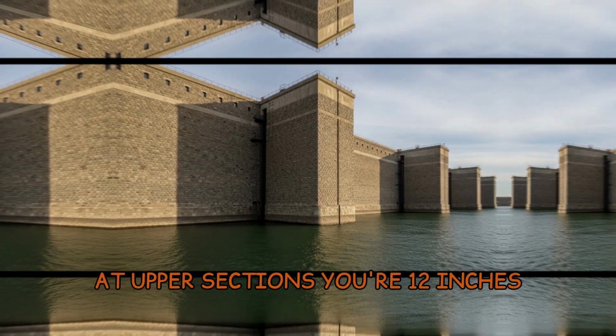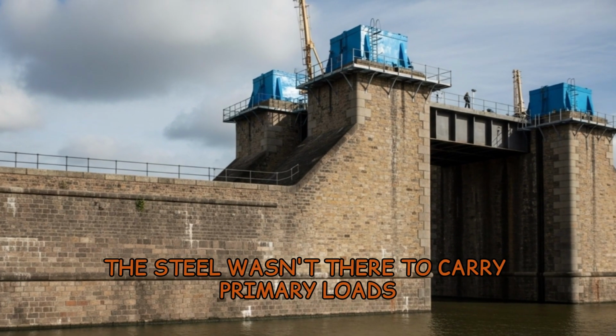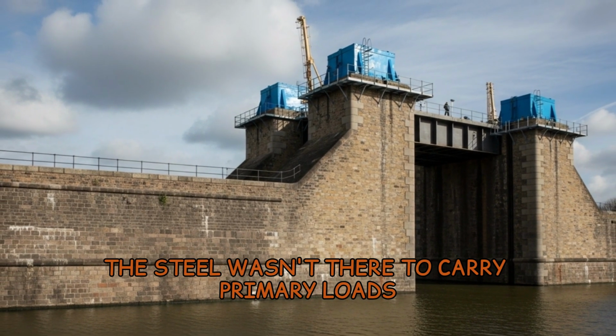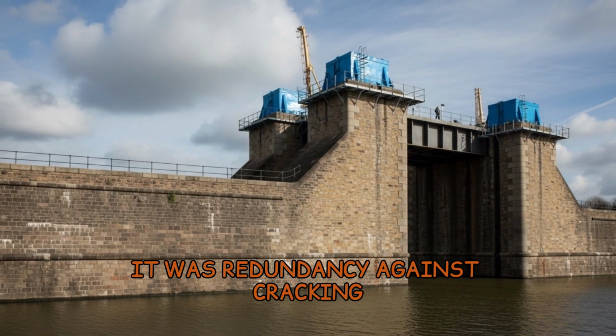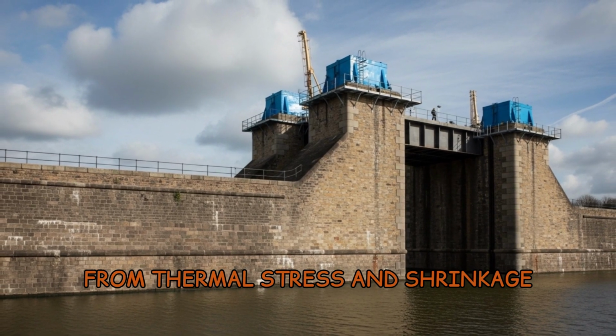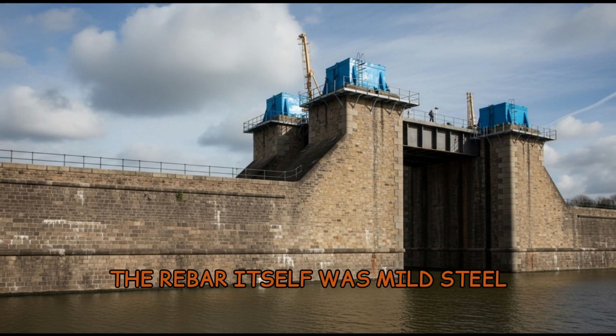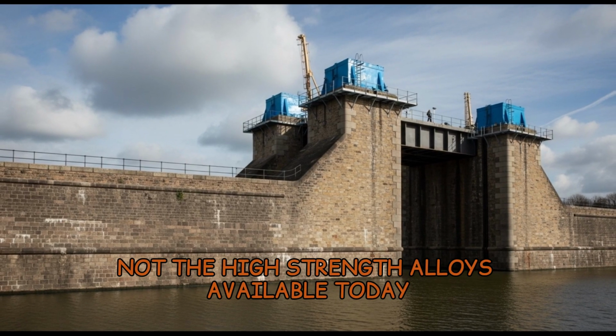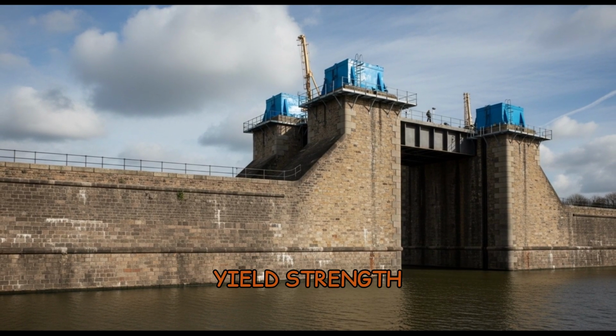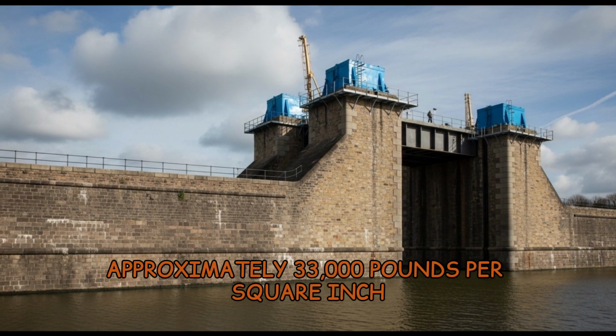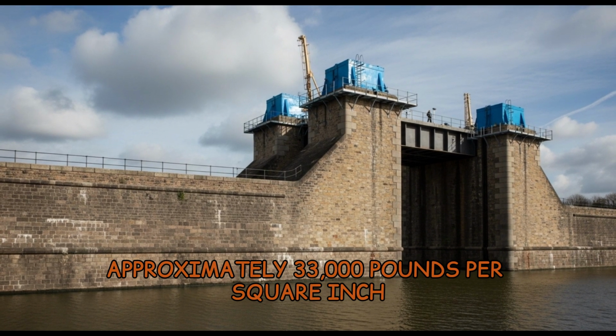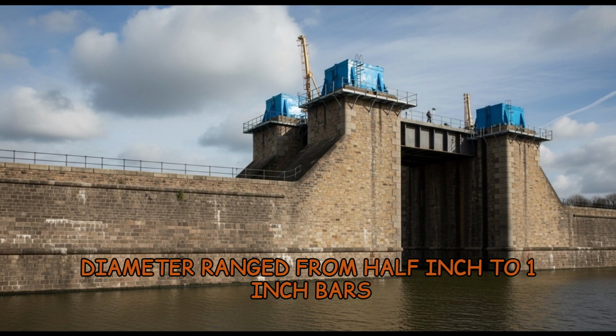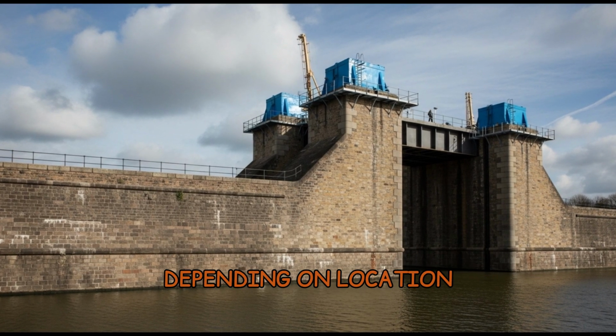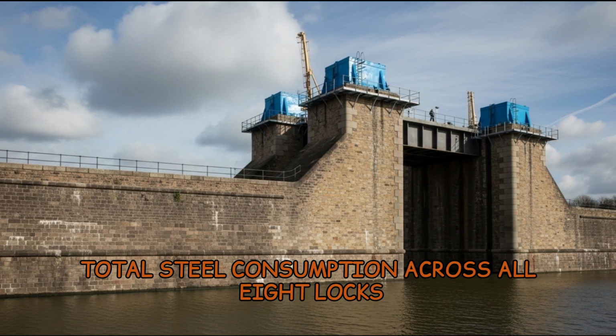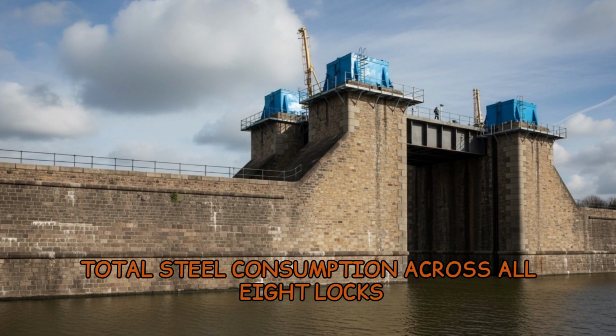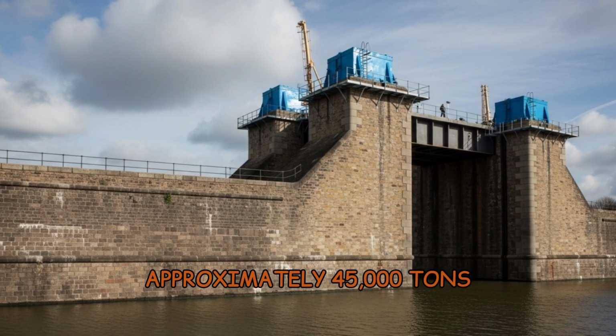At upper sections, 12 inches. The steel wasn't there to carry primary loads. It was redundancy against cracking from thermal stress and shrinkage. The rebar itself was mild steel, not the high-strength alloys available today. Yield strength approximately 33,000 pounds per square inch. Diameter ranged from half-inch to 1-inch bars depending on location. Total steel consumption across all 8 locks, approximately 45,000 tons.